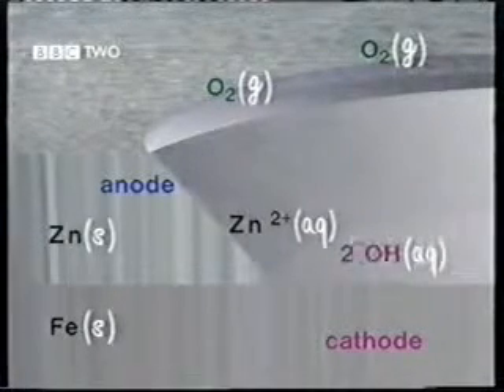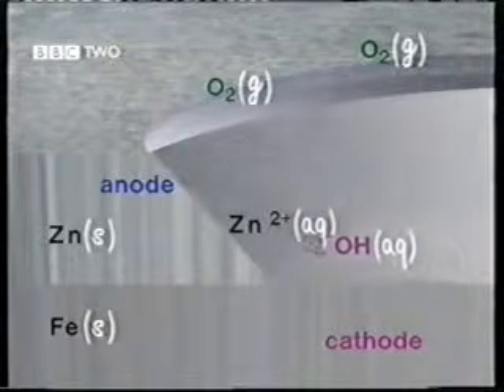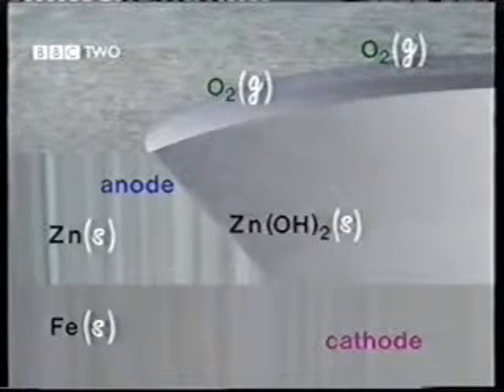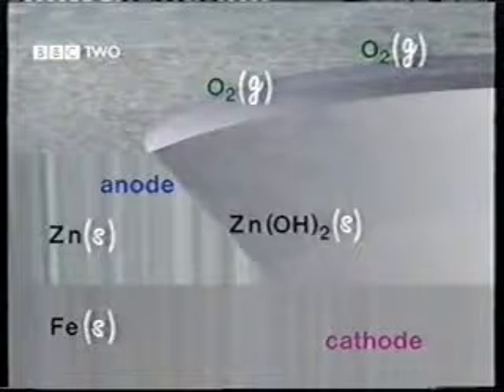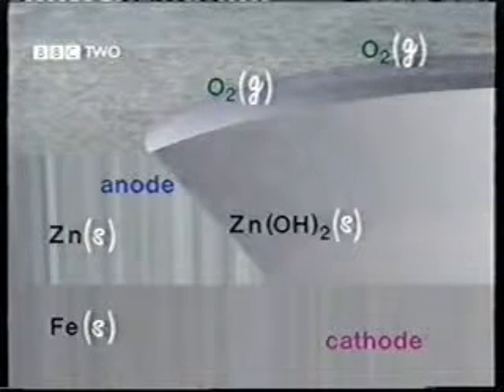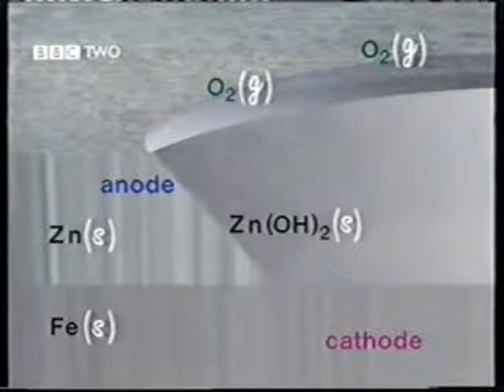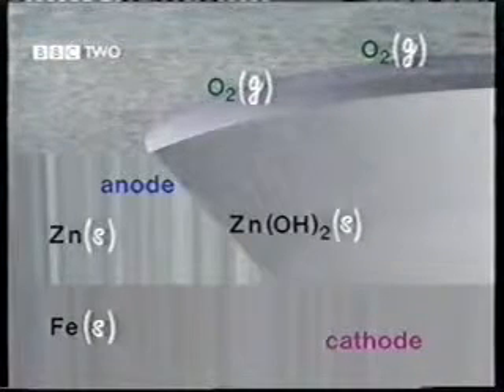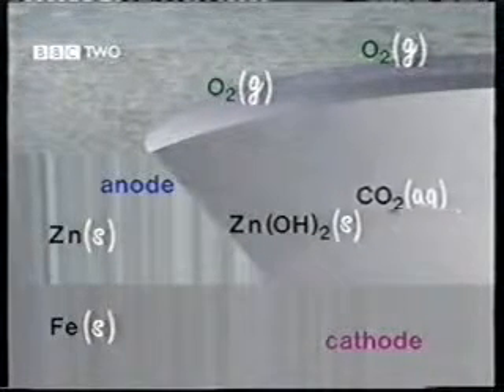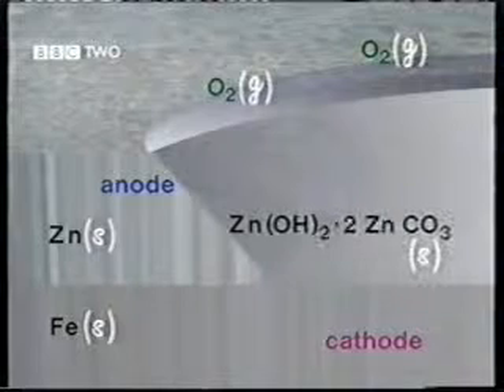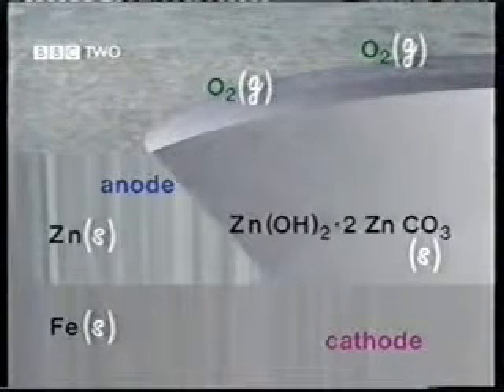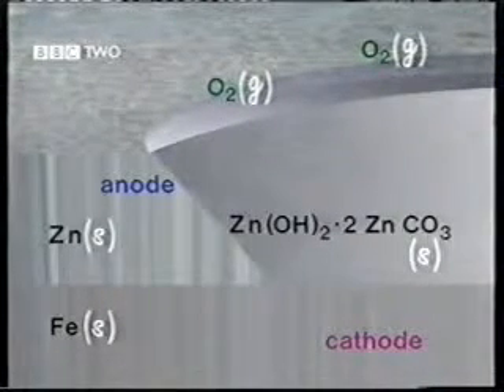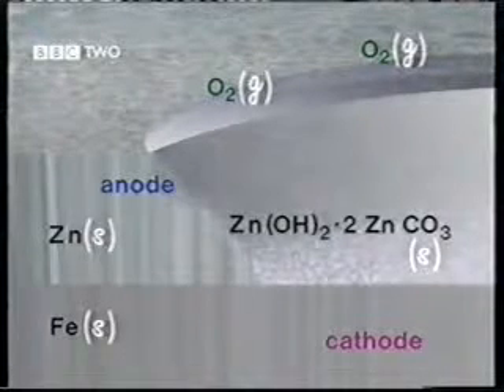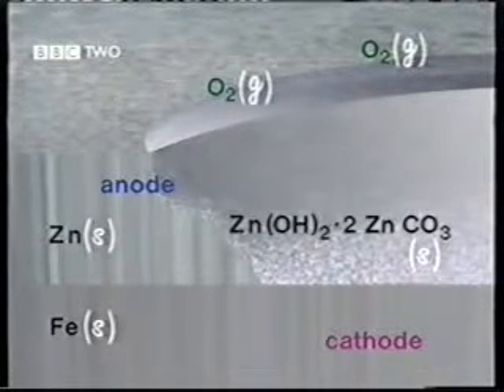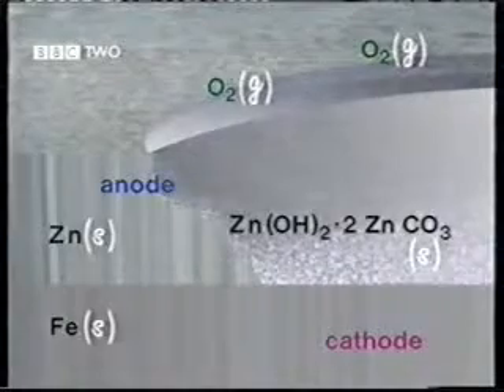The hydroxide ions produced combine with zinc ions to form zinc hydroxide on the zinc surface, and also to a limited extent on the exposed steel. This is an example of galvanic corrosion. A basic zinc carbonate is also formed by a reaction of the zinc hydroxide with carbon dioxide dissolved in the water. These corrosion products partially protect the exposed area, and the damage is partly self-healing.